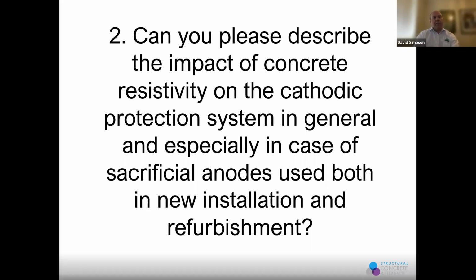Initially, just the premise, galvanics have a limited voltage. If you think of Ohm's law, your current is related to your resistance. So the higher your resistance, the lower your current. So people were concerned that if we had very high resistivity concretes, then you would limit the performance of galvanic systems. And there were figures initially used at around 15 kilo-ohm centimeter.